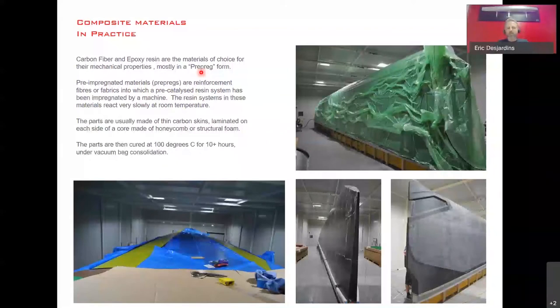And when you're ready, when you've laminated all your fiber on the mold, you can set up your vacuum bag and you can cook the part in the oven at about 100 degrees. It's a long cook. It takes about 10 to 16 hours to cook a part, and you do it two or three times until you have the finished part.